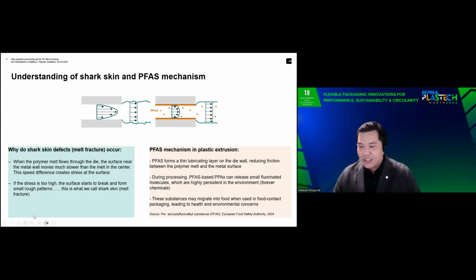Before the detailed insight, I'd like to brief you a bit about shark skin and the conventional PFAS mechanism in the blown film process. When we use metallocene LLDPE resin in blown film applications, we might find shark skin or manufacturing defects during the process. The reason is the difference in velocity profile at the center of the polymer melt versus the edge as it passes through the die.